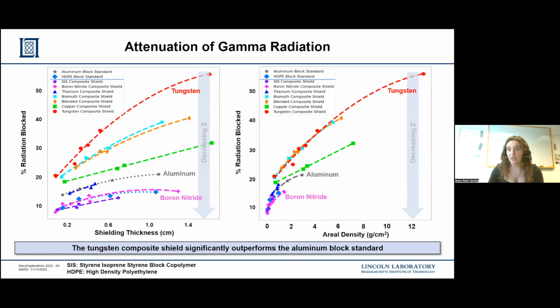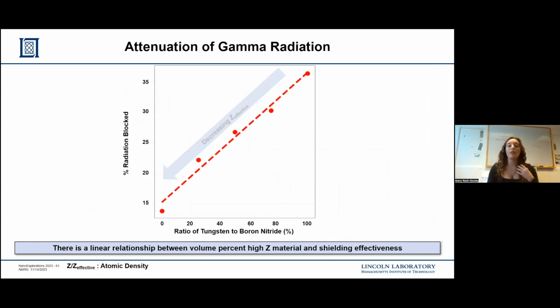Because gamma radiation is prone to elastic scattering, our high Z material, tungsten, outperforms all of our other shields. And it does so in both shielding thickness and areal density. As you can see, a lot of our shields also outperform the aluminum block standard, with aluminum being what we're currently using.